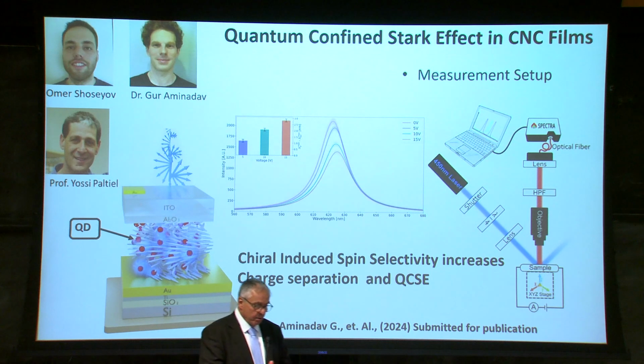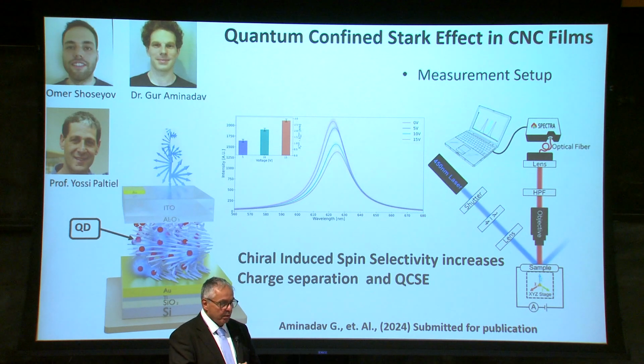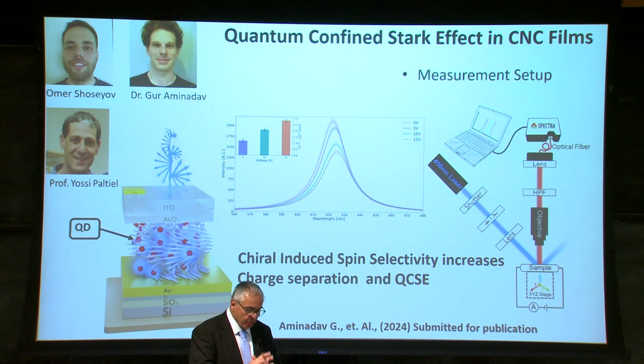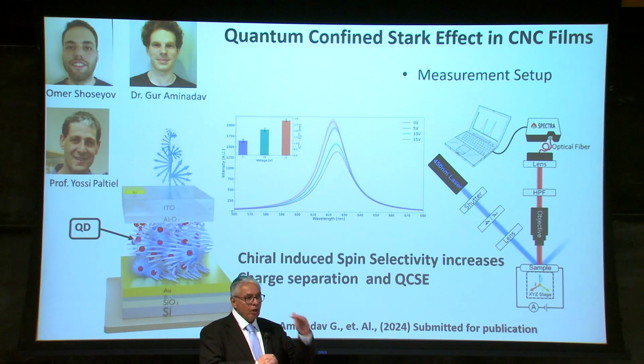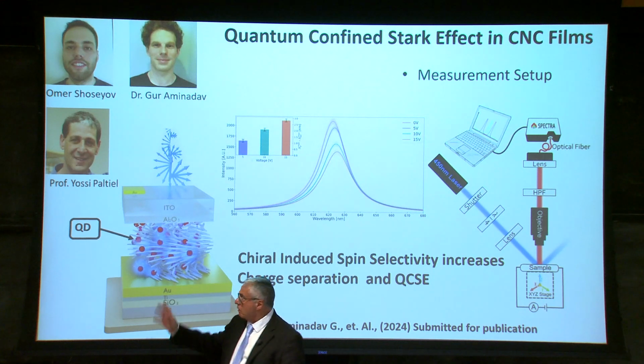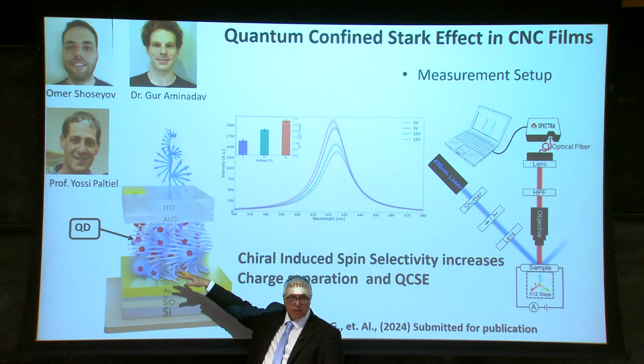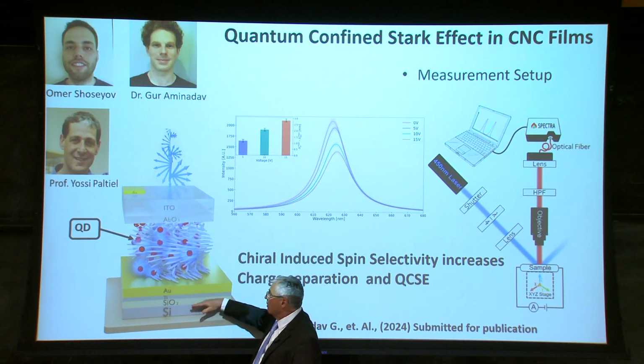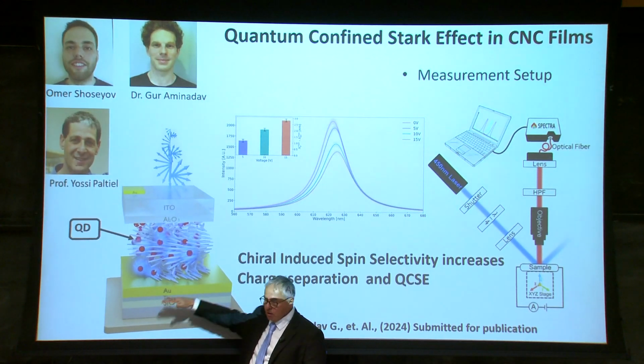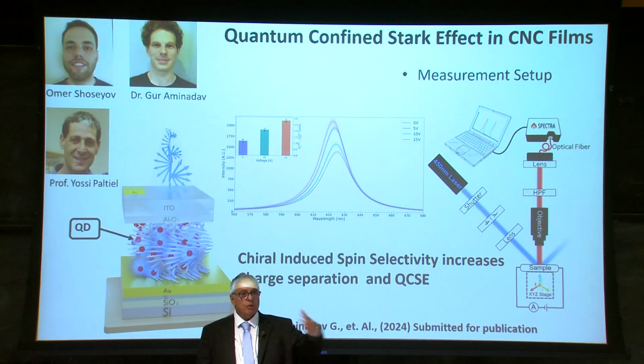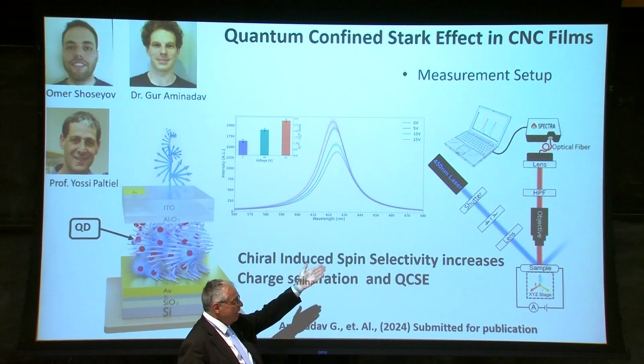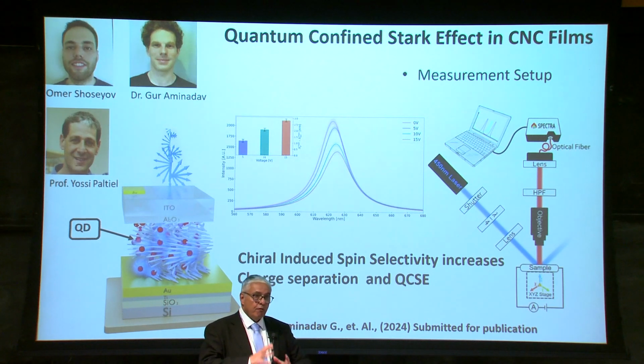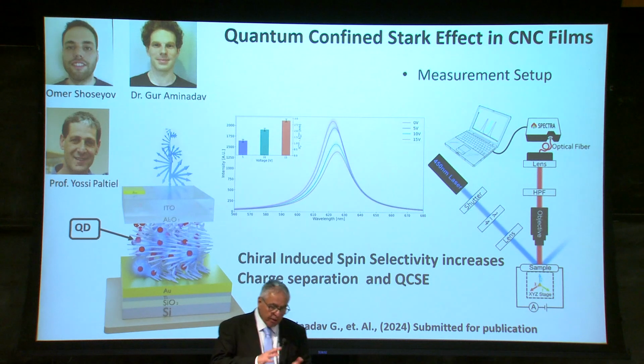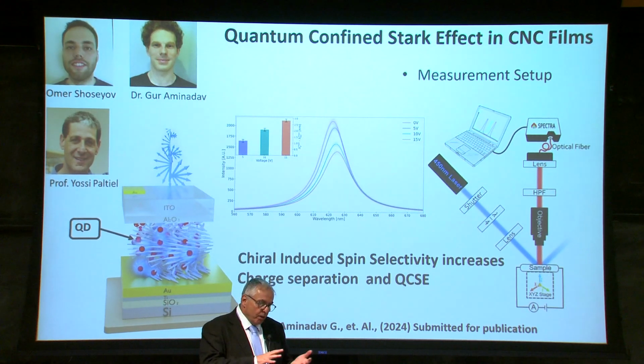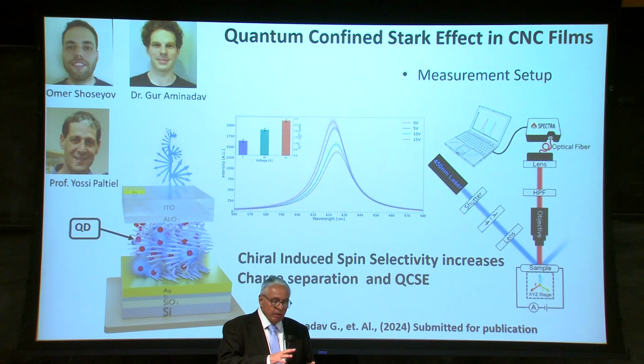With another graduate student, Dr. Gur Aminadav, who got a PhD before in computer science and is now doing his second PhD, we were able to show some really interesting features of cellulose nanocrystals combined with quantum dots. You can see the design of the device here. We have cellulose nanocrystals, which of course have this chiral nematic structure, and in red, quantum dots. At the bottom, you have one conductor, which is the gold, and on the top, we have the indium tin oxide, which is a transparent conductive material. When we shine a laser on it, we can do a very effective charge separation. The reason for this is that the material is chiral, so we have this chiral-induced spin selectivity that really increases the charge separation.